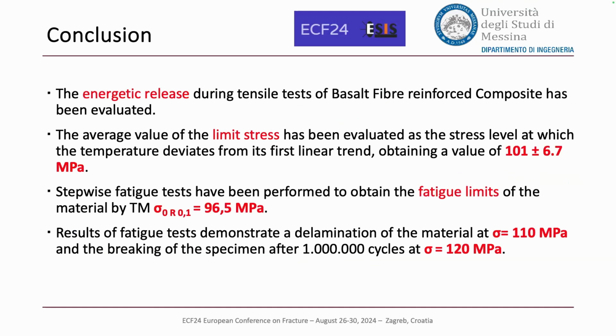I am at the conclusion of my presentation, and I want to summarize my results. The energetic release during tensile test of basalt fiber reinforced composite has been evaluated. We found the limit stress with the static thermographic method of about 100 megapascal. The thermographic method provides a fatigue limit of 96.5 megapascal, and the constant amplitude fatigue test demonstrated the delamination of the material at sigma of 110 megapascal and the breaking of the specimen after 1 million cycles at sigma 120 megapascal.